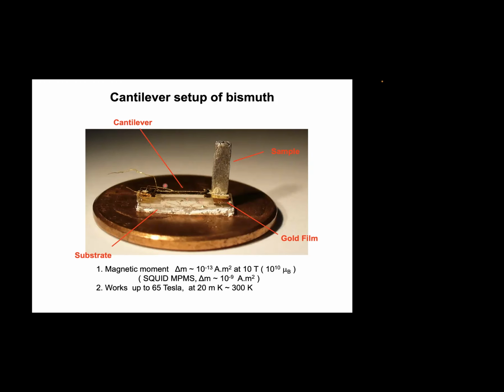It's just straightforward capacitance measurements. That means as long as we have a probe with good coaxial cables, we're able to adapt. That's how we adapted to 45 Tesla for this particular study. Now these days, it's up to 60 or 70 Tesla in Los Alamos, where we're able to use their probe to go to the pulsed field facility for the capacitance measurements and eventually for the magnetization.